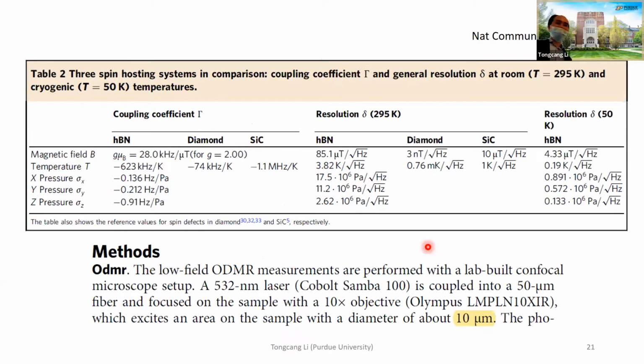They measure that. By the way, their sample is a bulk sample. They use a 10x objective lens, with a spot of 10 micron. So basically they collect the signal from a lot of spin defects with a resolution of 10 micrometer. In their case, they report a magnetic sensitivity of 85 microtesla per square root hertz, which is quite worse compared to diamond emission, and a temperature sensitivity of 3 Kelvin per square root hertz, and so on.